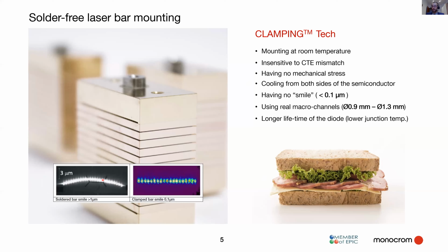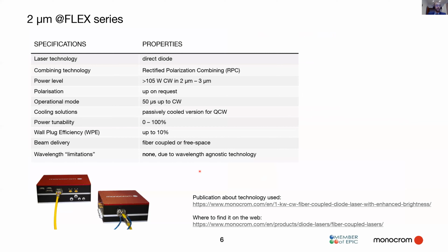Our laser bars, luckily, do not have solder material, so the position of the emitters is mostly determined by the flatness of the electrodes. And these can be really flat. As you can see here, the variation of the emitters is less than 0.1 micrometer. And we can ensure this even for our stacks. Another advantage of our non-smile laser mounts and laser bars is that these are superb starting conditions for external resonators, which we are using in our high-power fiber-coupled diode laser modules, which I will explain now.